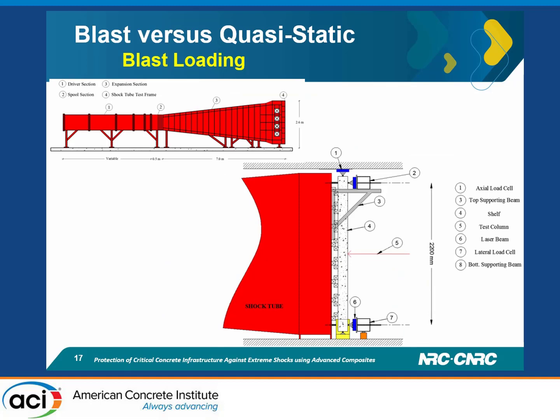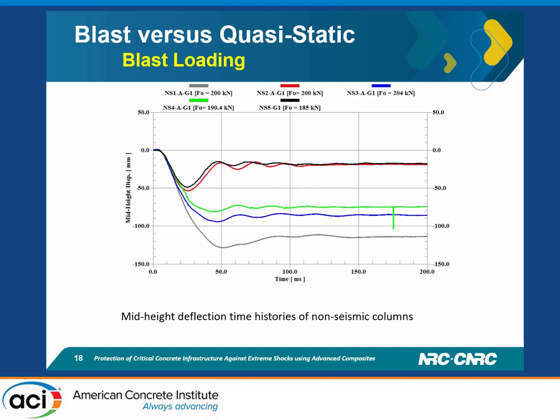And here is a simplification of the system, a sketch showing the lateral load measurements at the top and bottom, and we also use laser devices to see the deformation and high-speed cameras to monitor the test itself. We analyze all the strain and the strain waves throughout the formation of the plastic hinge and so on. Here is a sample of the results, and as you can see, with the FRP the residual deformation is very low, while without FRP the residual deformation is extremely high. And in this test we use only a single shot, not multiple shots. It's just one single shot which results in failure.